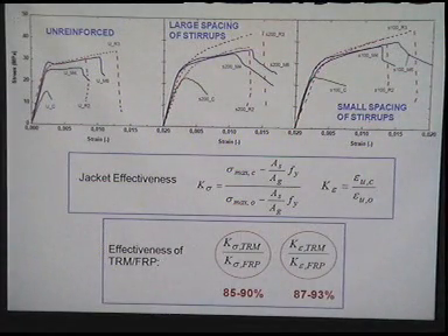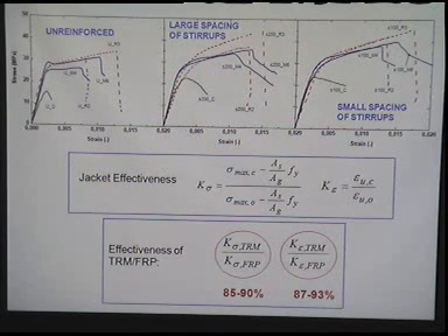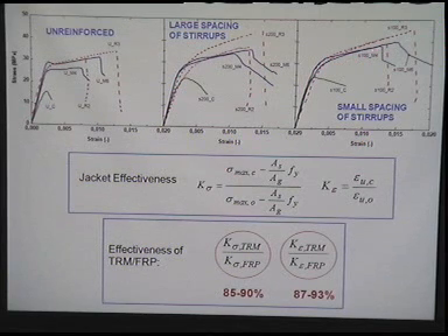We don't have to look at all those curves. Just remember that in each family of those curves, green is the response of the concrete prism without any jacketing. Blue curves correspond to the response of the specimen with TRM jacketing, and red curves correspond to the response of the specimen with the FRP. So if you compare blue and red, you see that they are not that far apart. The effectiveness of those systems is similar to that of the FRP system.